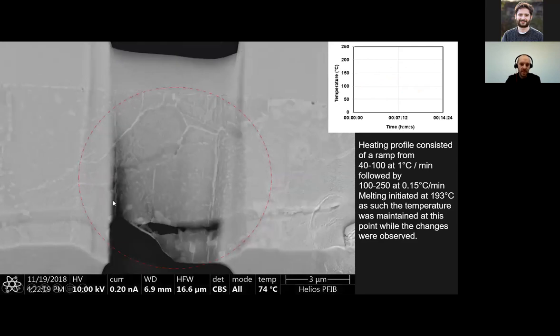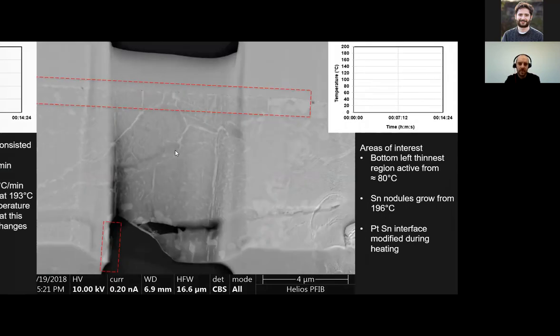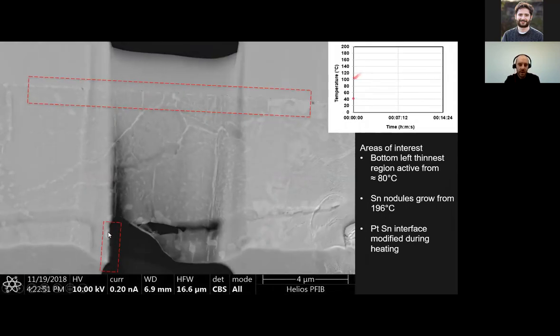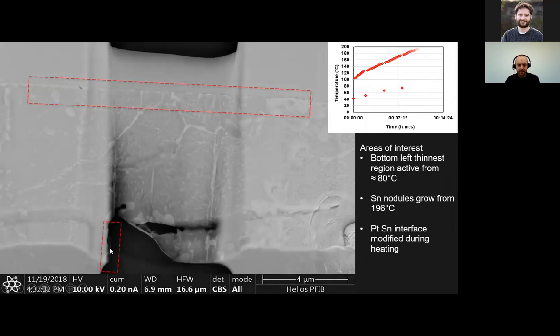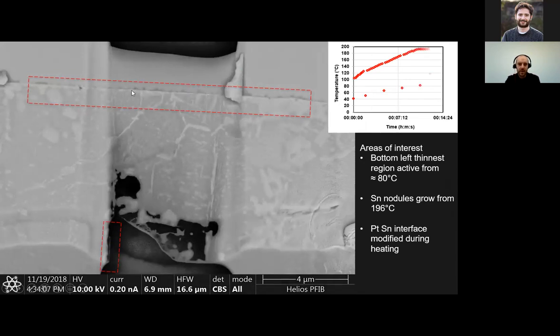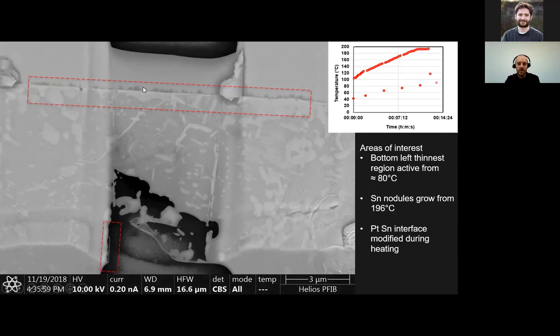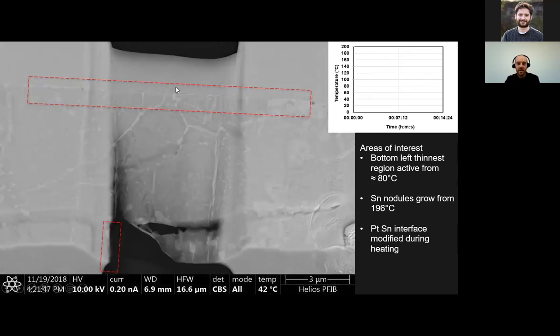What we can see has happened is, initially, we'll go through it this way. You start to see the precipitates moving in the bottom left-hand corner. They're starting to form together and produce new precipitates. And then on the top edge, we can start to see diffusion from the tin into the platinum layer, and also tin nodules forming.